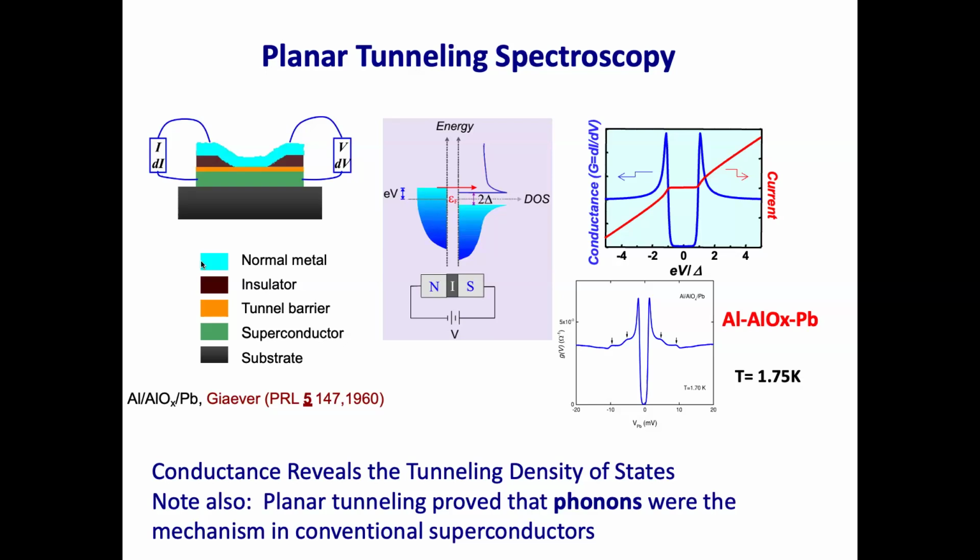This is what proved the BCS electron-phonon theory of superconductivity, right? So what's happening here is that in conventional metallic S-wave superconductors, most of the periodic table we think, it's electron-phonon mediated. I don't think I have to explain this here. So what happens when you're down at low temperature and you go superconducting and then you go tunneling from the superconductor to the normal metal, the tunneling electrons that get through actually feel that phonon. You can actually calculate it, we understand it.